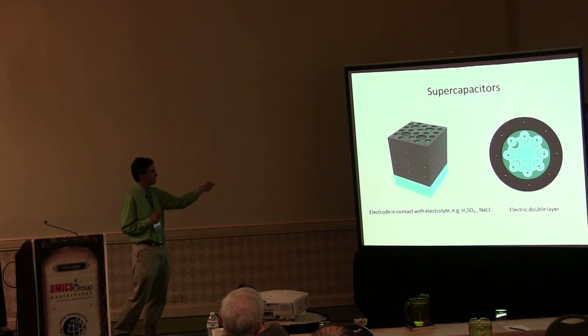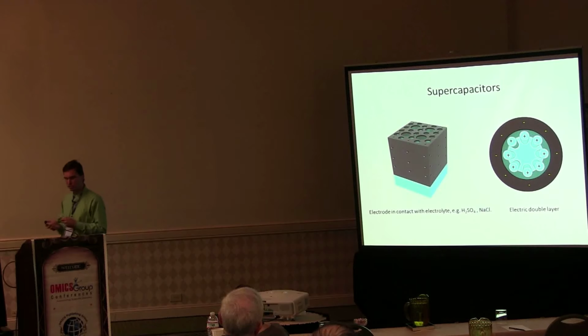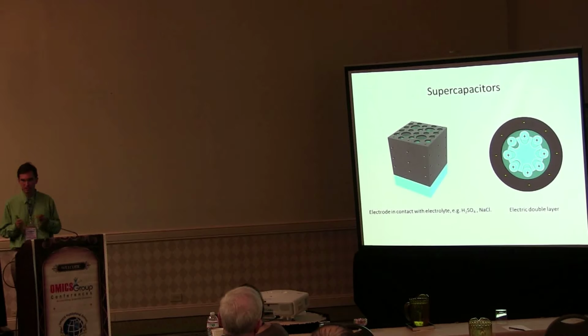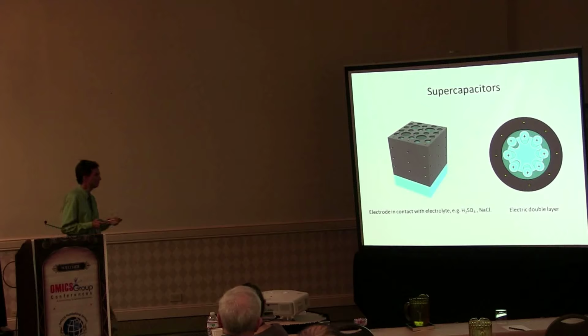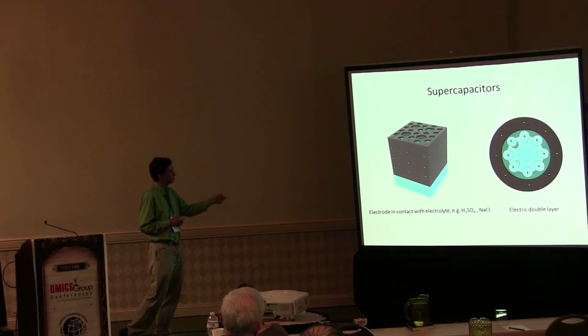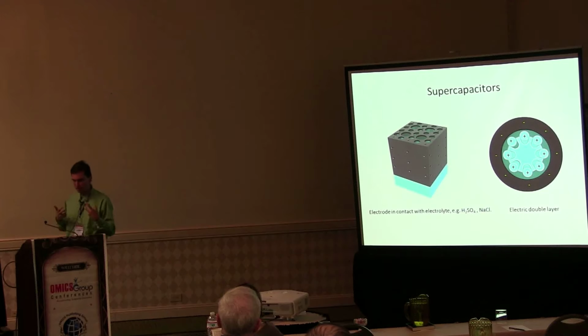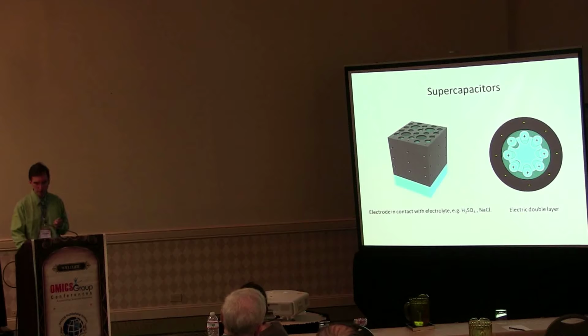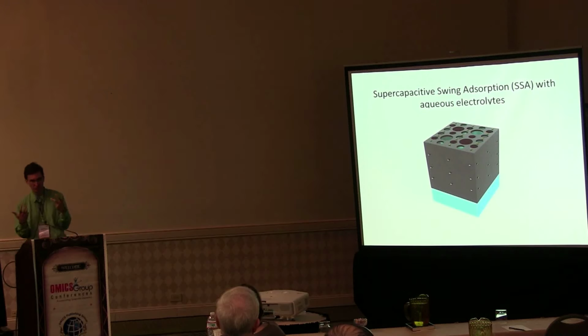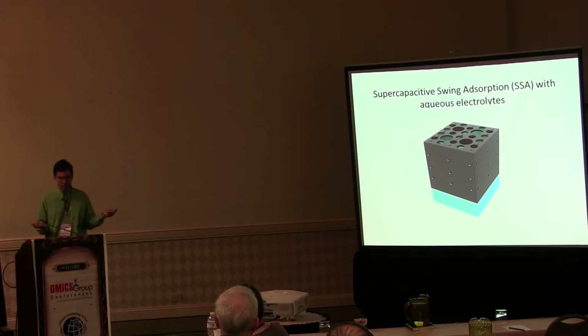Using a supercapacitor for our approach, however, poses an additional difficulty. The pores are expected to be filled with the electrolyte. So given that, how can we still achieve gas adsorption? We believed that this picture of a nanoporous carbon material with completely filled pores is not quite the correct picture, because in a nanoporous carbon material, you have a random structure with different surface functionalities on the pore surfaces. Some would be expected to be hydrophobic, for instance, CH functionalities. Some would be expected to be hydrophilic, for instance, carboxylic acid functionalities or keto groups.